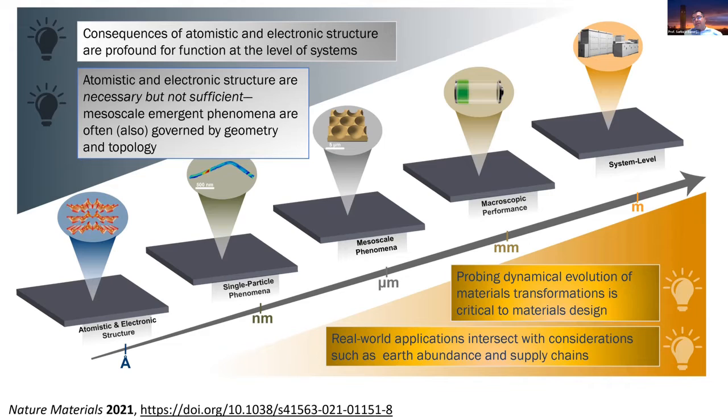We saw several examples of that, but also to use probes like EDXRD, where we're probing layer by layer in a real cell or something that looks like a real cell, and looking at the effects of tortuosity and particle porosity and particle geometry on the cathode. And the entire thing is important both from the perspective of accessible rates as well as chemistry, electromechanics, electrochemistry, mechanics coupling, and so on and so forth.